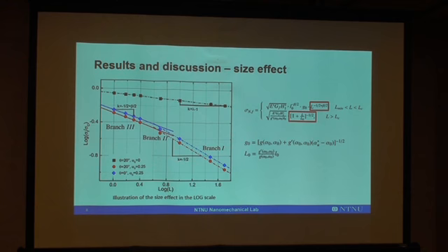The size effect here suggests that if we are doing a nanomechanical test at the grain level to calibrate the decohesion parameter, then the calibrated parameter might not be a material constant, because it is size dependent. And this law here might help us to bring it under control.